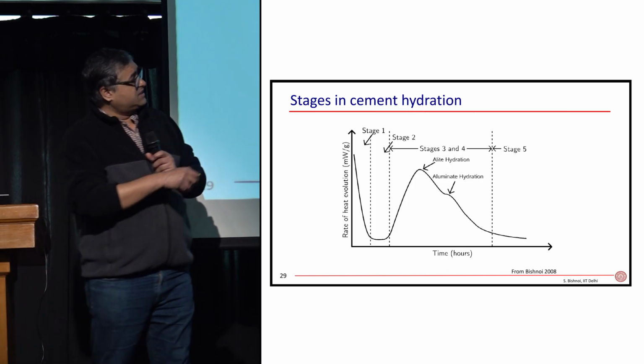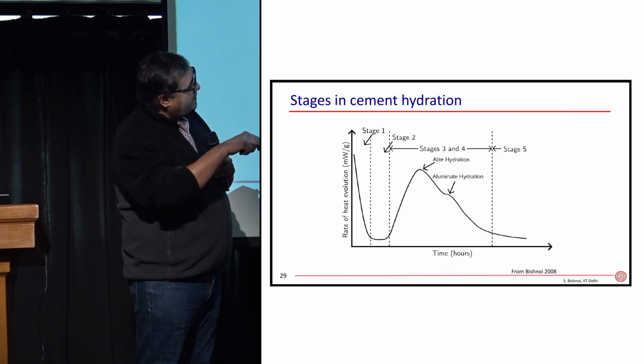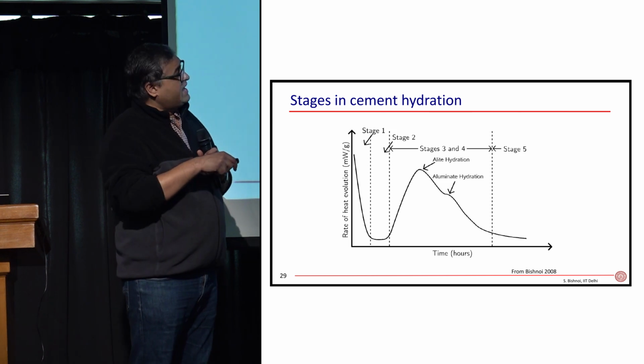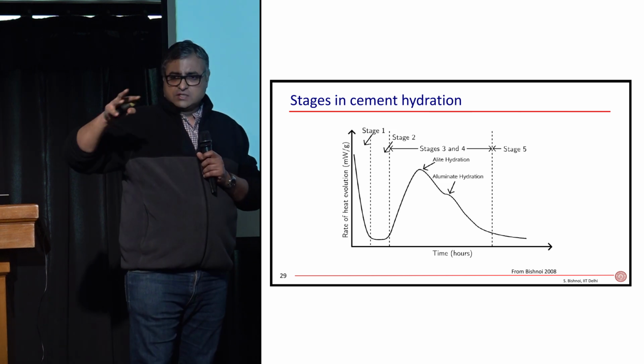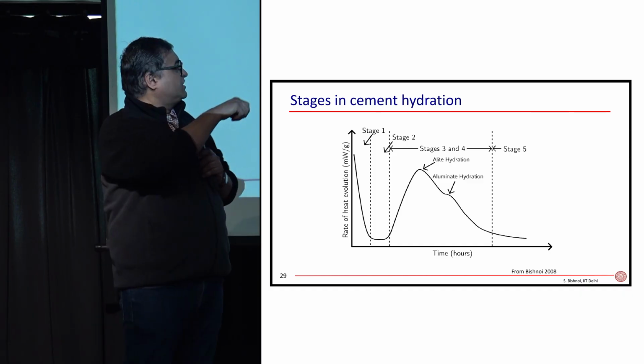When you carry out this test, you should see a proper peak appear, and then a second hump - a sharper hump - appearing after the softer peak.